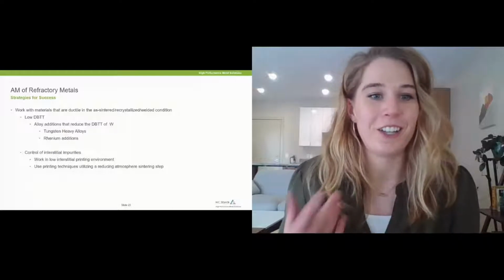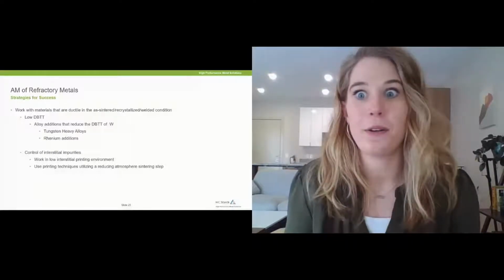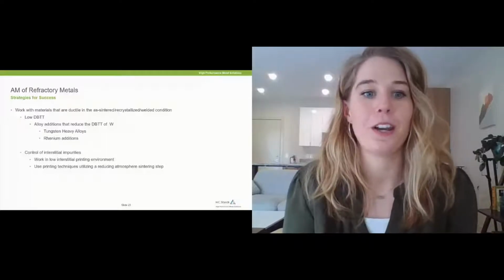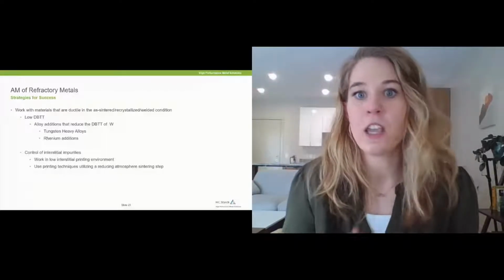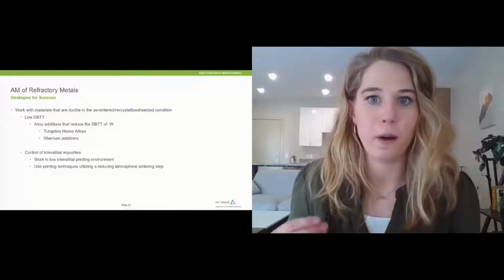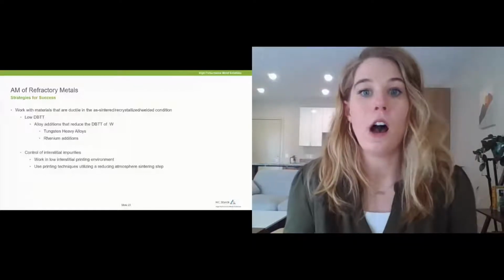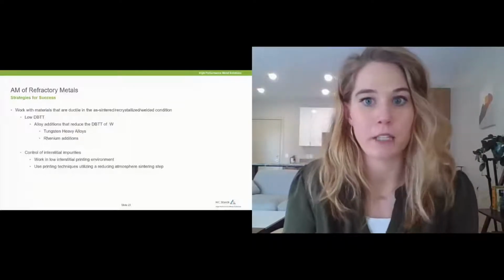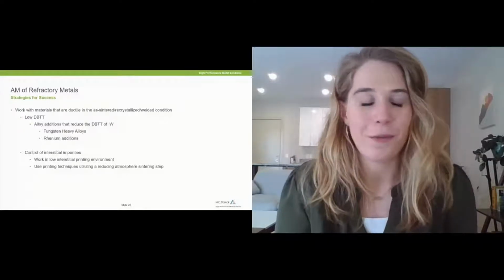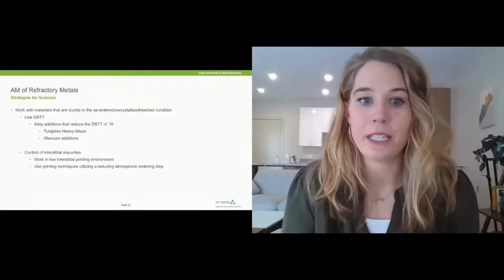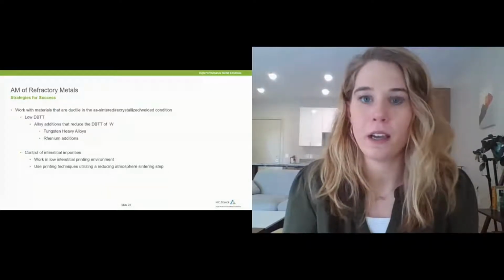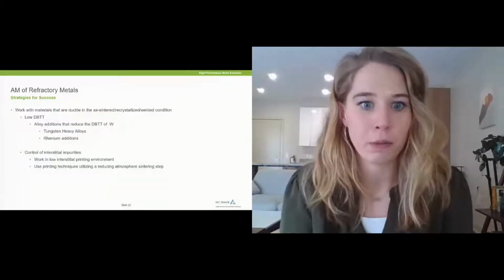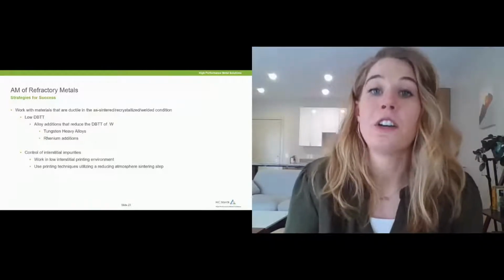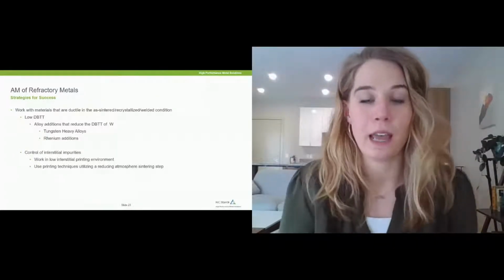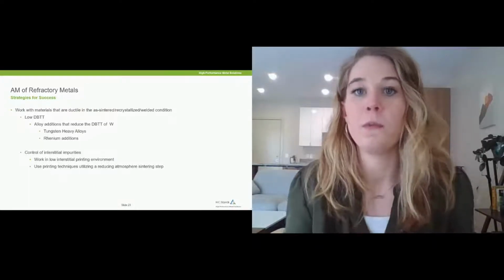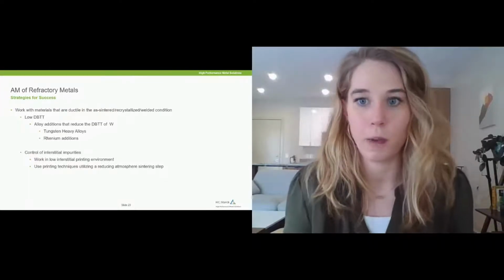Again, I'm going to bring in the control of interstitial impurities. So now it's extremely important to work in a low interstitial printing environment. So making sure that when you're printing, you are in an inert atmosphere with as low an oxygen content as possible. Another strategy that we have implemented is using a reducing atmosphere when you're using sintering technology such as binder jet or screen printing. So instead of using an inert atmosphere, you're using a reducing atmosphere to remove as much oxygen out of the system as possible.